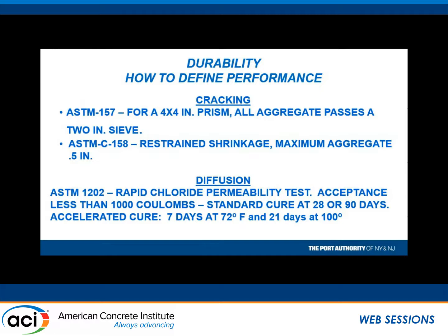So anyway, we talk about how do we spec shrinkage. Colin said, spec it. All right, here you go. Here are the tests. Here are the two used in the industry. C157, maximum size aggregate, 2-inch. I'll show you the JFK runway. We have up to 10% aggregate retained on a 2-inch sieve. Does it make a difference in the shrinkage test if you have 2-inch aggregate? I think it probably does. So is this a good indication of shrinkage? The restrained ring shrinkage test, maximum size aggregate, a 1/2 inch. If all this is supposed to do is give you an indication of the paste shrinkage, then maybe it's worth something. Diffusion, ASTM C1202.